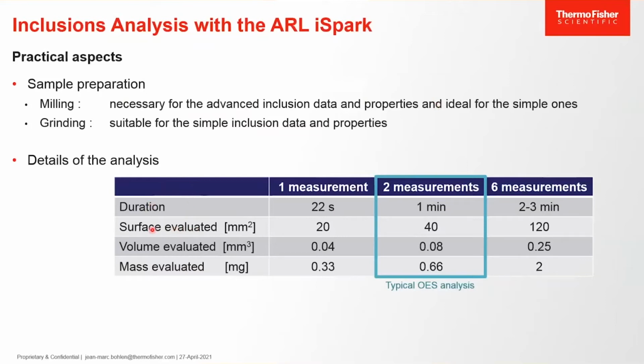Interesting is to look at what surface of the sample is evaluated with our technique. So for two measurements, it's about 40 square millimeters of the surface where we look for inclusions. As you know, in optical emission, material is ablated. So the analysis is not a two-dimensional method, but a three-dimensional one. So we can talk about volume evaluated as well. And in the case of a two measurement analysis, the volume is 0.08 cubic millimeter typically. This corresponds to a mass that is evaluated of the steel sample of about 0.66 milligrams.